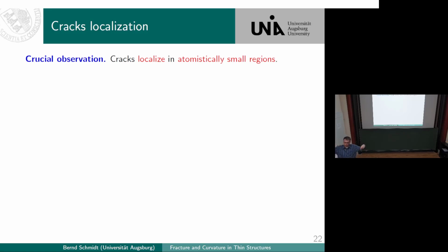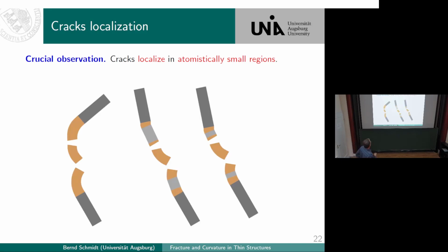What could happen is that you introduce a little bit of crack here, and then a little bit further crack here, and this is very nasty if the crack is getting too far. So what you would like to see is that all the cracks happen in a very small, atomistically confined region. Let me just show a picture of how we do this. Here you fix the boundary conditions for the cell problem. Now, if you really had a large region where fracture happens and also an elastic region, they're not bent like this, they're just bent a little bit; this is just in order to see something on the slide.